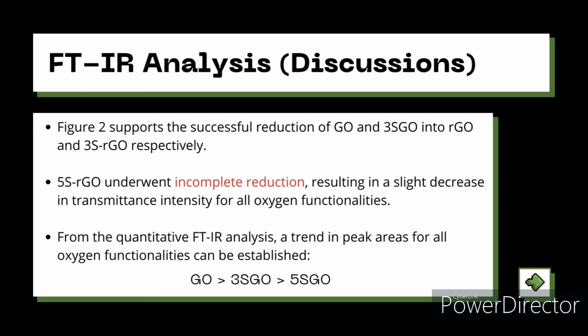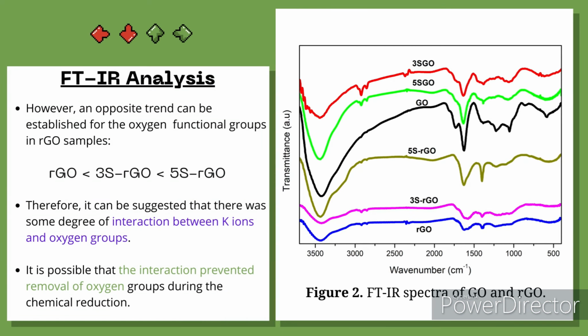Firstly, for GO, the trend in calculated peak areas for oxygen functionalities is in descending order from GO to 5S-GO. For RGO, an opposite trend is observed where the degree of oxidation is in ascending order from RGO to 5S-RGO. Thus, there is some degree of interaction between potassium ions and oxygen functionalities which prevented the removal of oxygen during chemical reduction.